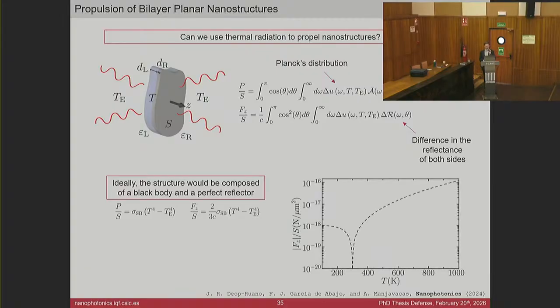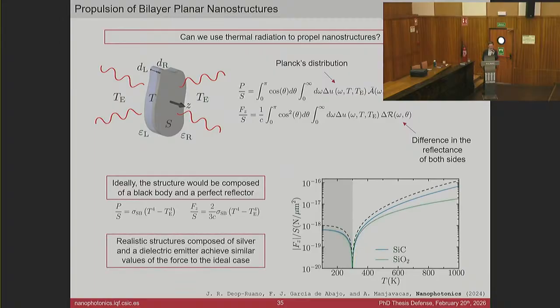We plot it. We can see that we can actually have a force that is highly dependent on temperature, and something interesting is that we obtain a positive or a negative force depending on whether the nanostructure is hotter or colder than the environment. Now, what is really important is that by considering realistic materials, we can use, for example, silver as a reflector and silicon carbide as an absorber or an emitter by reciprocity in the infrared. We can obtain results that are on the same order of magnitude as this ideal limit. We can also explore different configurations of nanostructures by changing the absorber layer, with varying results depending on the material.